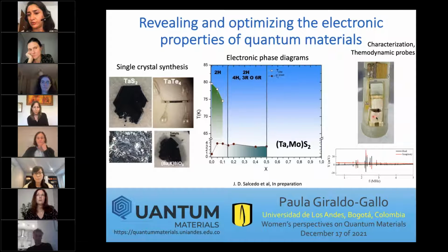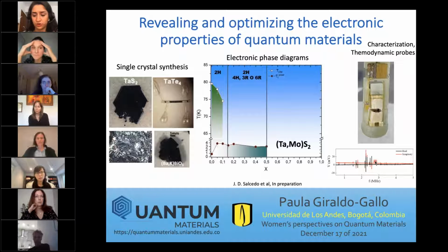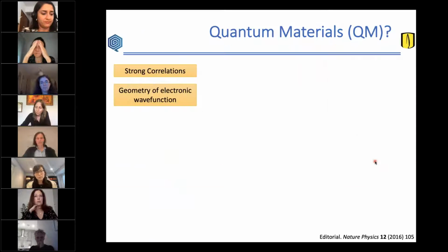So we put them under some piezoelectric transducers, and we measure the frequencies at which this material resonates, and we are able to obtain those sets of frequencies and therefore extract the elastic constant of this material, which is actually a tensor, which gives us symmetry-specific information on the thermodynamics and the evolution through phase transitions. So I'm going to give you some details on all of this story that I've been talking about. I'm sorry, my voice is kind of bad.